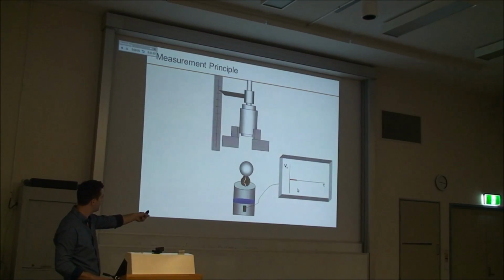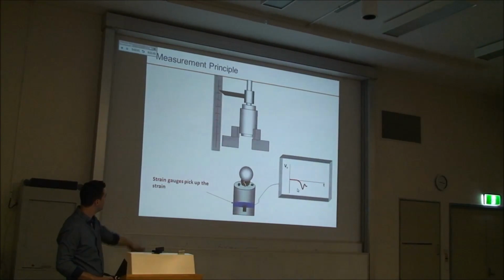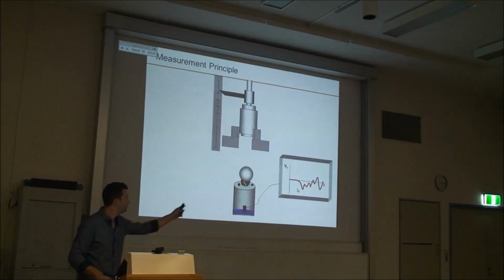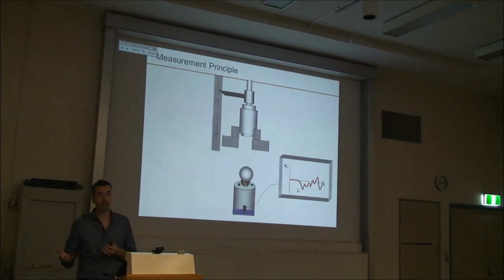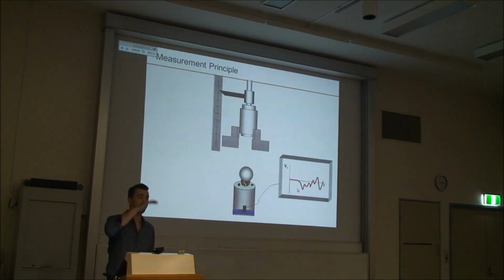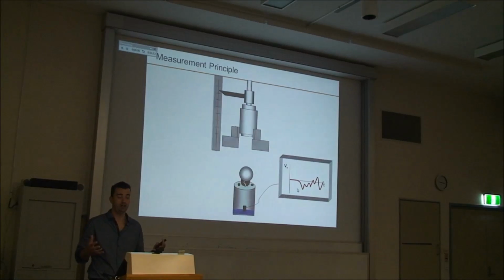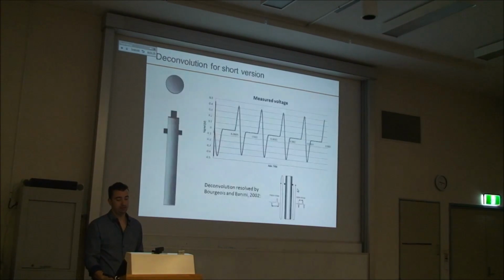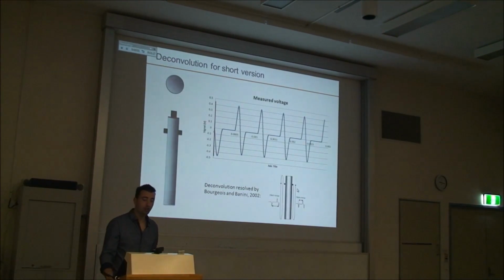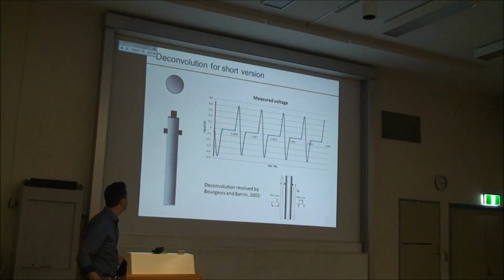The stress wave goes down in the rod, is sensed by the strain gauge, and then you record the signal. You record the voltage, and the voltage is related to the force applied on the particle. So then you have the force versus time profile. This is what is typically used in compression testing, where you look at the force and the deformation of a particle in the device. The short version of that is only 1.5 meters.